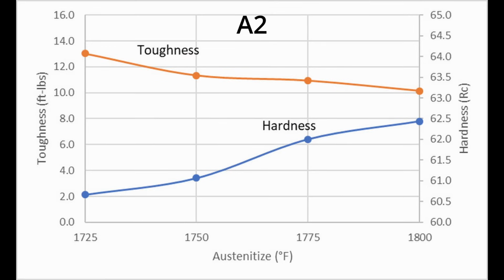Also, when I tested A2 with a 1700 degree prequench, we had to use that temperature or lower because the austenitizing range for A2 was like 1725 to 1775. It showed no improvement in hardness-toughness balance. So whether we're getting grain refinement or not, we're not seeing a clear improvement in toughness. If there is one, it's very small. And so I probably wouldn't dedicate a lot of time to doing a prequench.